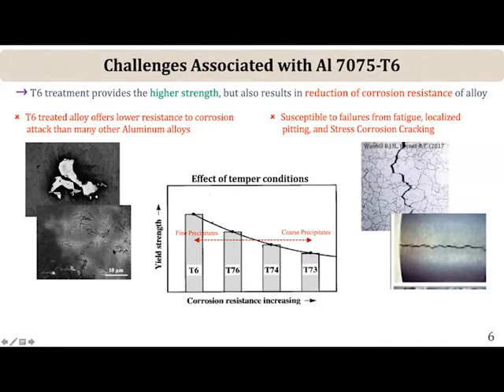initiating at those locations. So this is one of the problems, but what has been observed is that to some extent, one can control the corrosion and stress corrosion cracking by using the alloy in an overaged condition, as shown here. So the corrosion resistance generally tends to improve with these overaging treatments. However, there is going to be a loss of strength and loss of fatigue strength, as well as normal strengthening is going to be lost because of that.